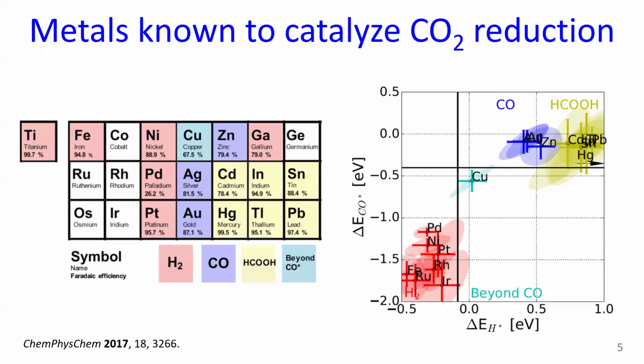Essentially, copper is the only catalyst known to make multi-carbon products with any significant Faradaic efficiency. And the reason for that is because it has an optimal binding energy for the various intermediates during the CO2 reduction reaction. I'll show later on that there's a vast distribution of different intermediates, and so balancing those different binding energies becomes very important. So we're talking about bulk copper, though? Yes.